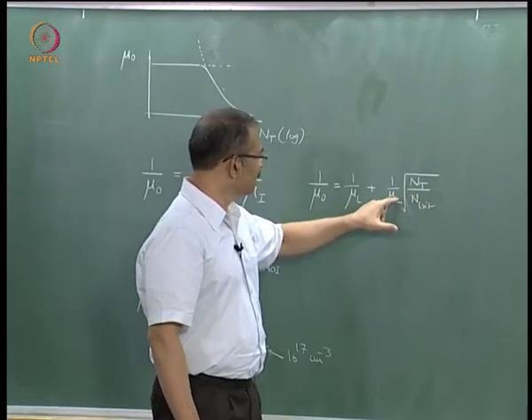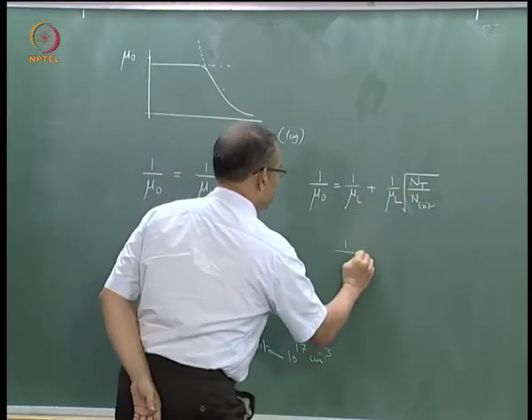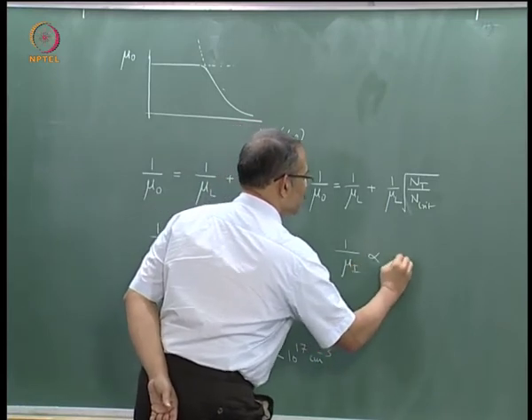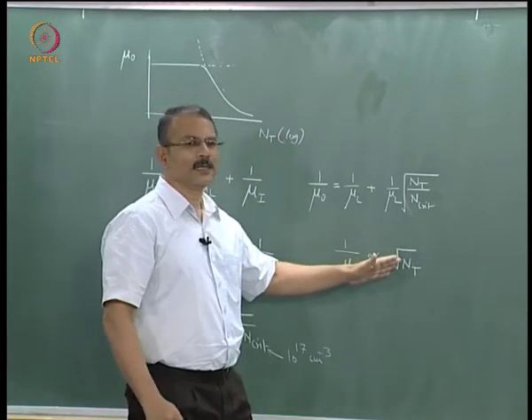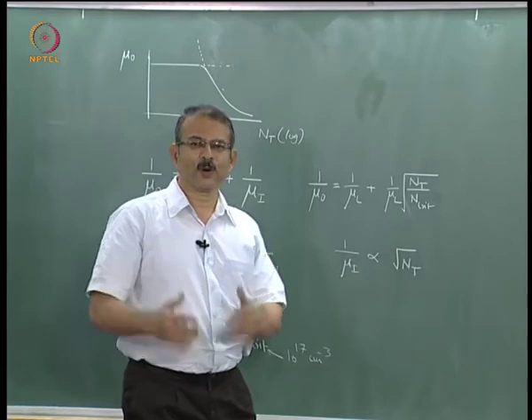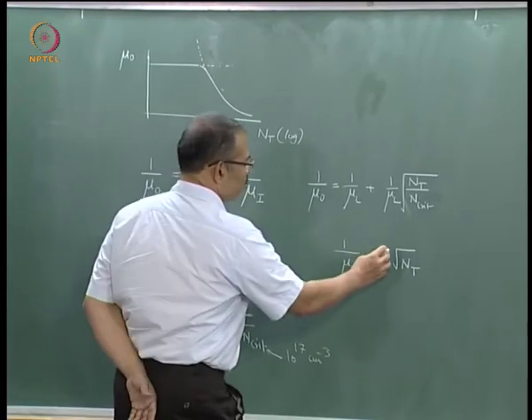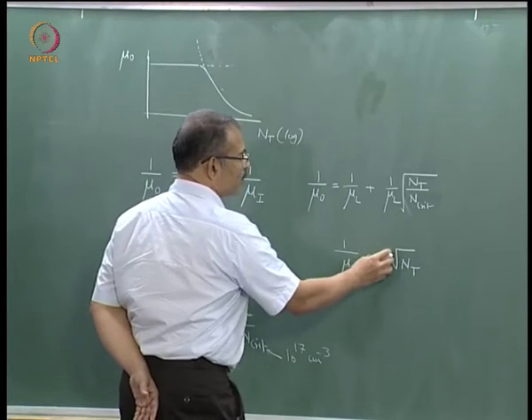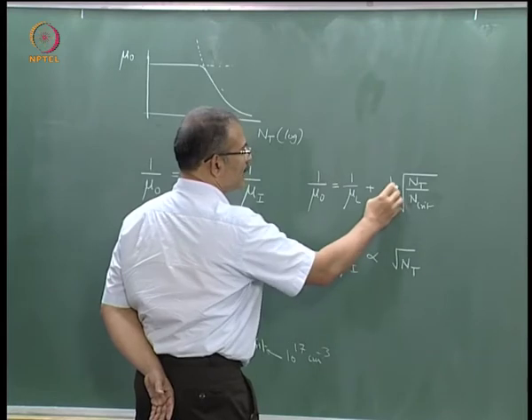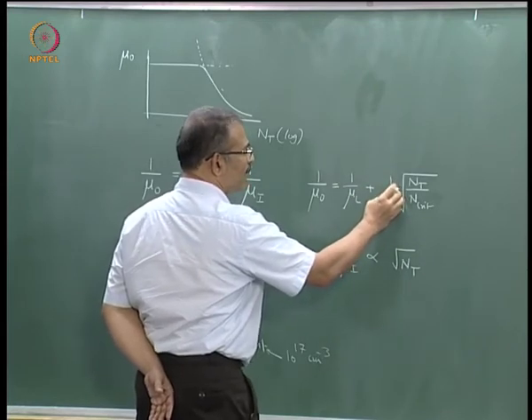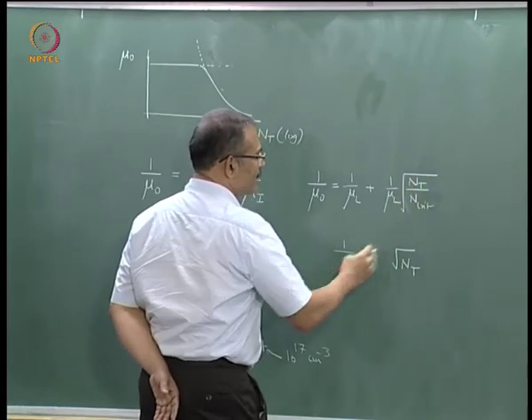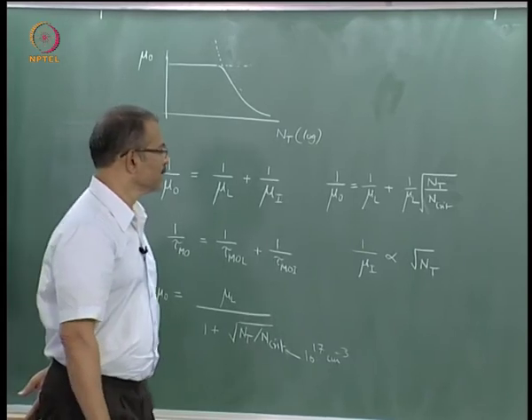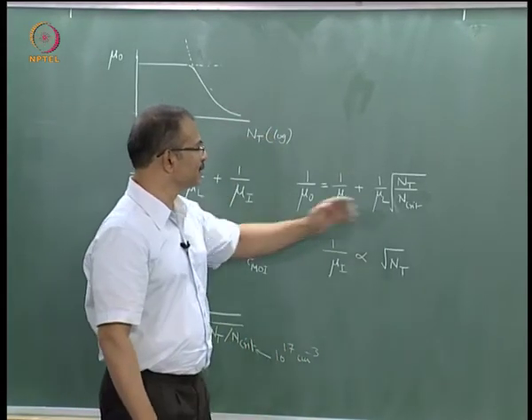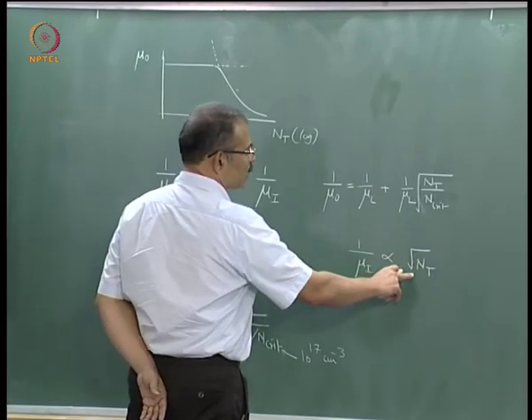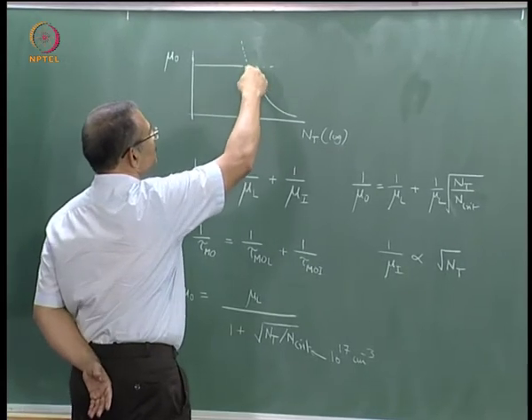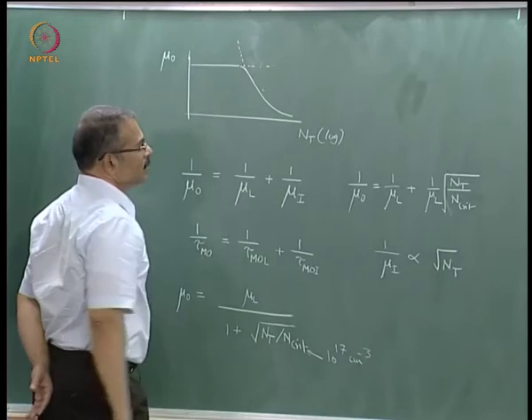Okay? And similarly, if you write the fact that 1 by mu I is proportional to square root of Nt, now evidently the square root behavior we have to get from quantum mechanics, we assume the result. So now we need a proportionality constant when I put an equality sign. Now that is where the proportionality has been achieved by using the mu L itself in the coefficient and then choosing an appropriate doping so that the behavior matches what you derive from quantum mechanics. Okay? So that is how one gets this relation. Now how do you get a relation like square root? So you see here that your mobility is falling and this part of the curve is 1 by square root, right?